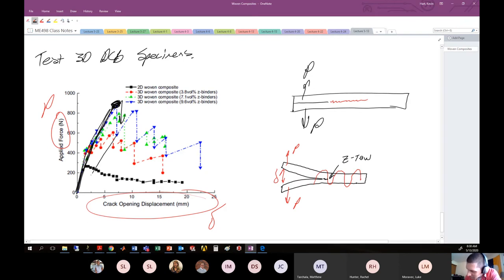So we know that the amount of energy that gets released during this process is something like the area encompassed by this particular portion of the curve. That was the energy released during that fracture event. And if that crack propagated a small amount between these fiber toes, we're talking a couple millimeters, then the energy there is just insane compared to what a fracture event would be like in this particular guy that has an energy that looks like that. So the change in energy between these two situations for the same crack advance is like 30 times. All right, it's an insane amount.